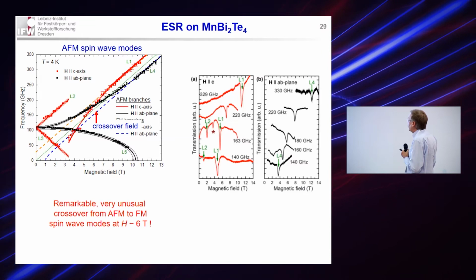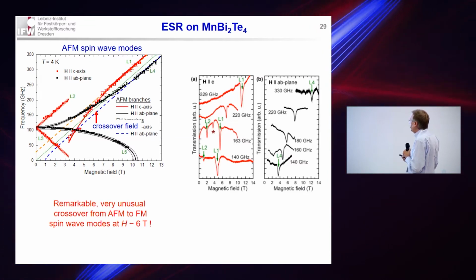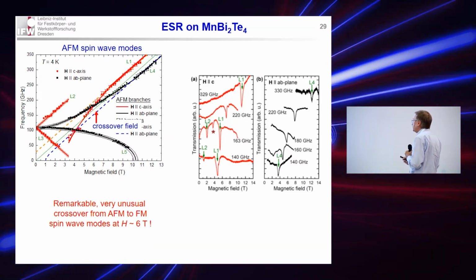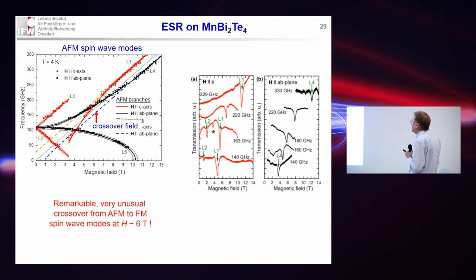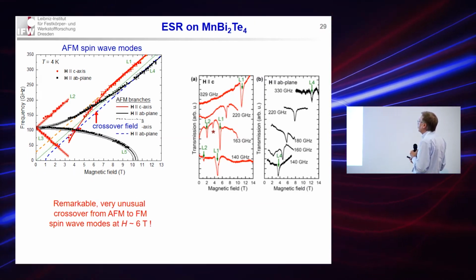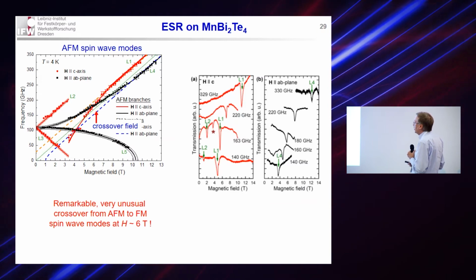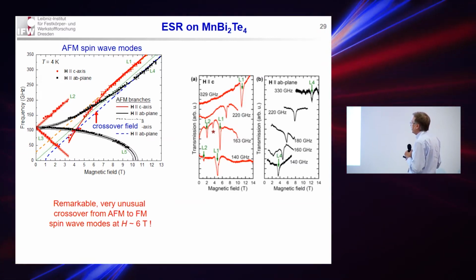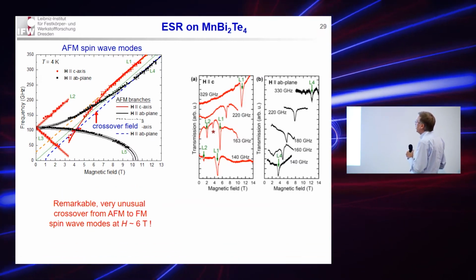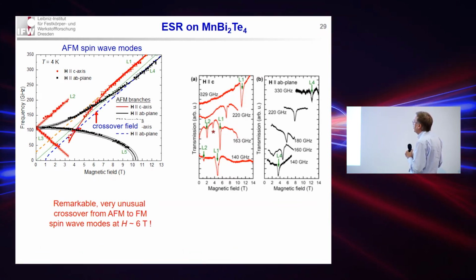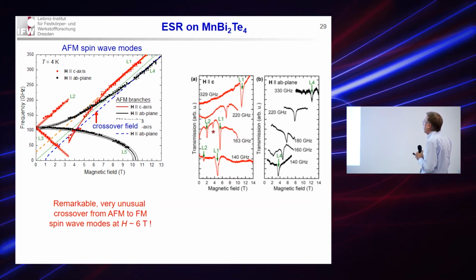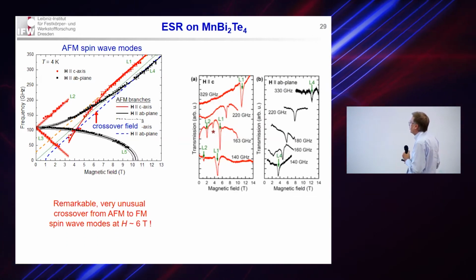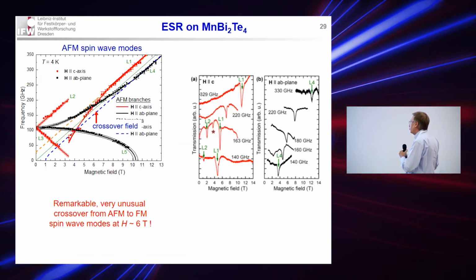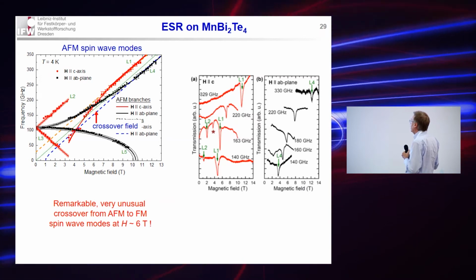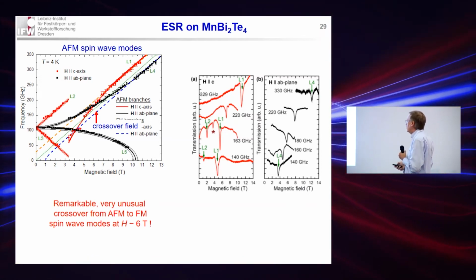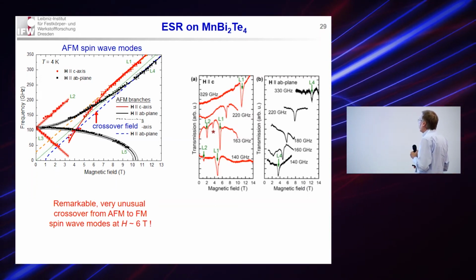Actually, if we just consider the high field region, above the crossover field, the modes are exactly the same which we observe for the 1-4-7 material. These are just sketched by these dashed lines. This is the ferromagnetic modes which we observe in 1-4-7. And actually, these antiferromagnetic modes at low fields turn into ferromagnetic modes at higher fields, which is quite unusual.